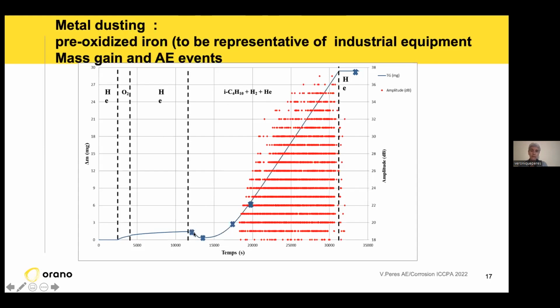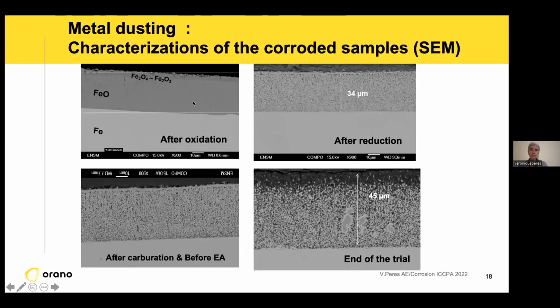And so we have this mass loss, which represents the reduction, and after that a linear mass gain, which is very interesting here, a linear mass gain of the sample inside the waveguide, and we begin to hear some noise due to the corrosion, to the insertions. So this is very interesting because we have quite an induction time here, and then the corrosion and the production of noise due to the cementite decomposition.